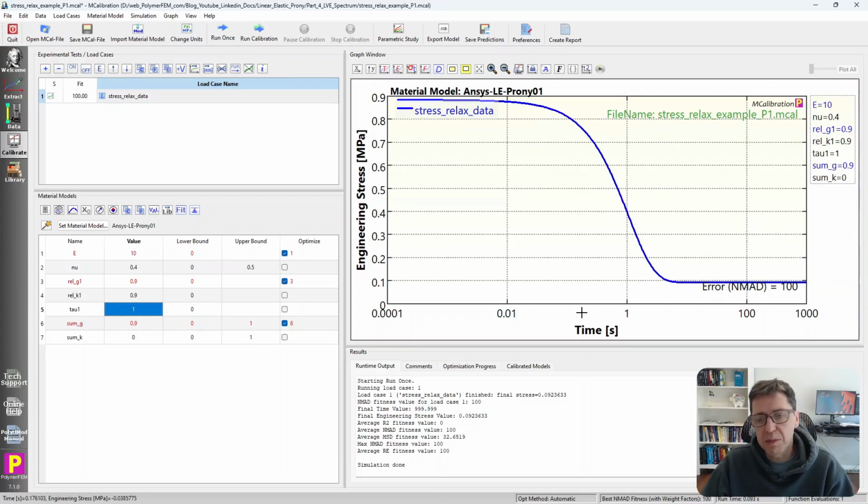And there's nothing particularly exciting about it. A single Prony series term will do this, and this is the significant result that it doesn't usually match the data, because you can't specify the whole response at longer times. So experimentally, it doesn't always happen this quick. You need to have a different shape to this curve. And that's why people come up with the Prony series to superimpose a number of these exponential curves. Now, with a spectrum, things get much easier.